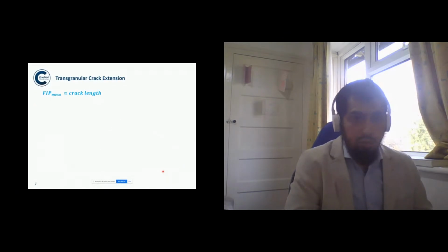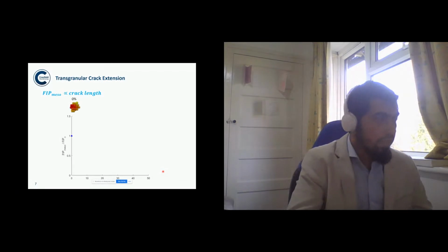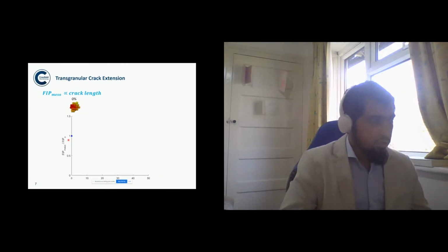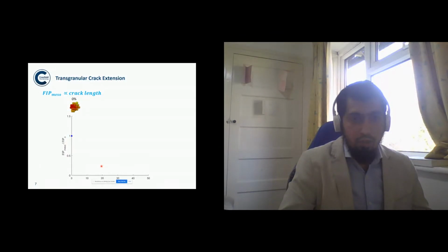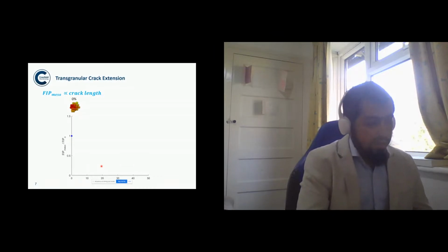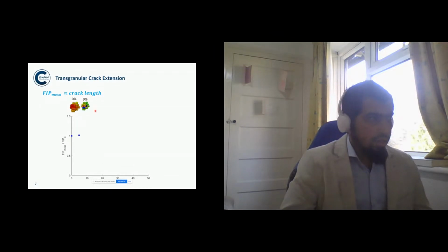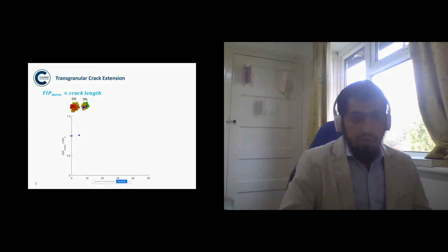Now, the next step is to extend the crack along that band. So in this figure here, we have this minimum life band, and in this plot down below, on the y-axis, we have the average FIP normalized by the average FIP at 0% crack extension. That's why it is 1. And on the x-axis, we have the distance along the minimum life band. We extend the crack by deleting a certain amount of elements of that band, roughly 9%. And these deleted elements are shown by the blue color in this figure. These elements are no longer available in the simulation, so they are termed deleted elements.